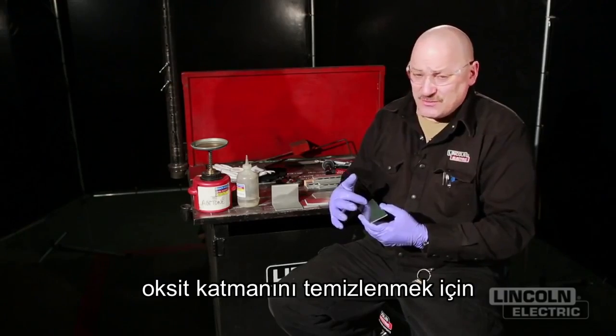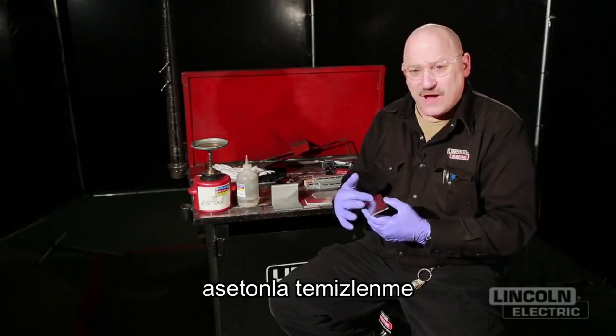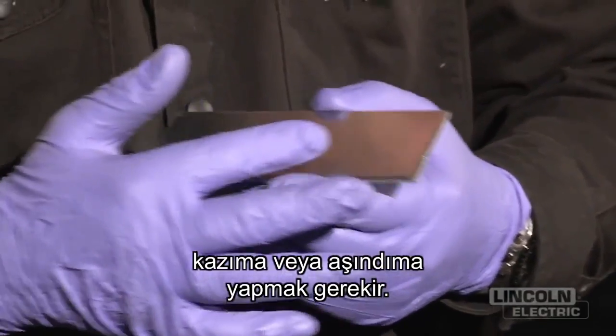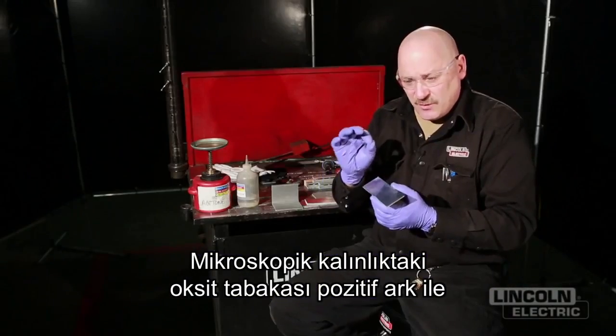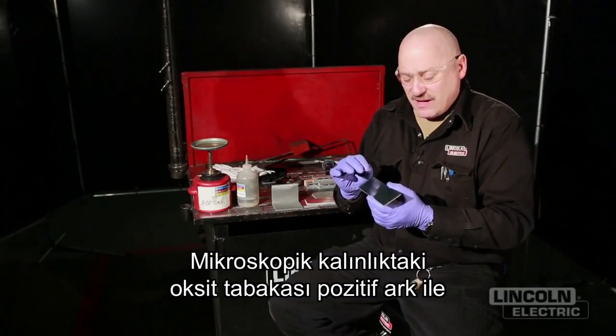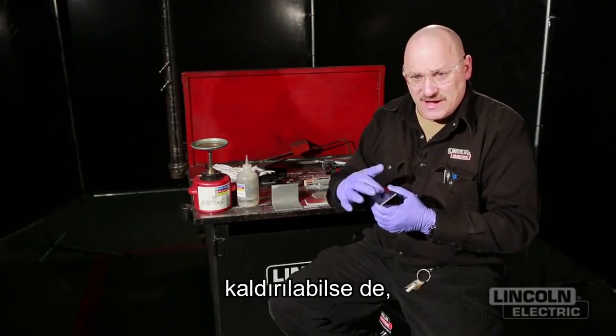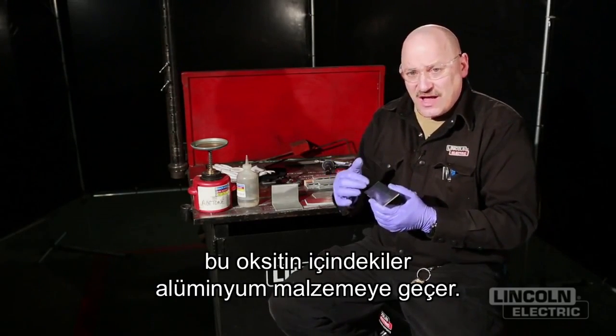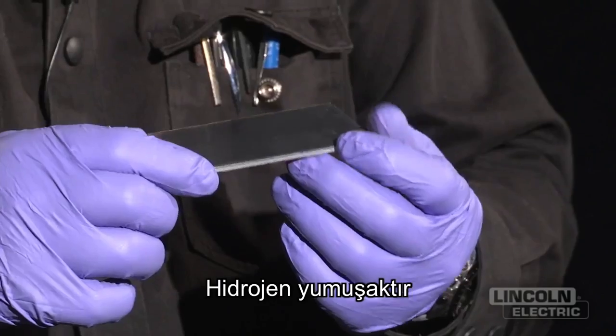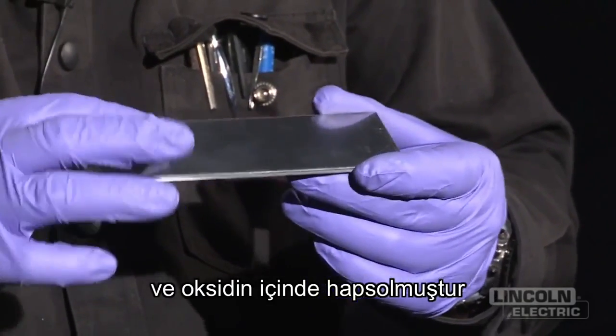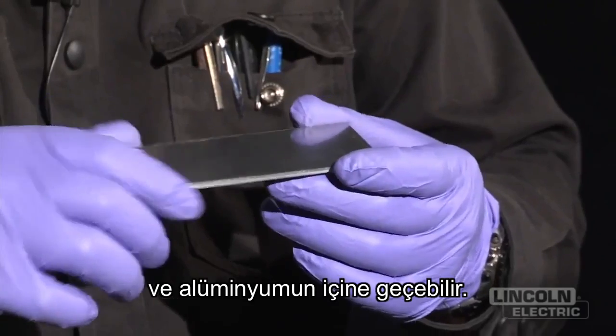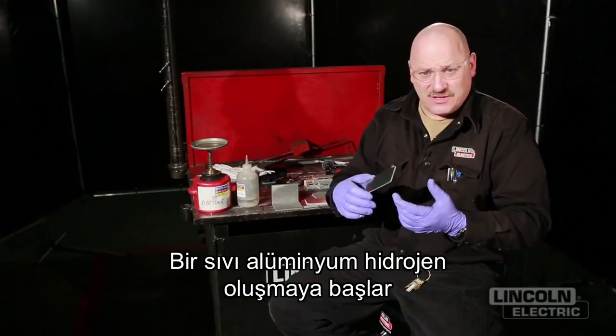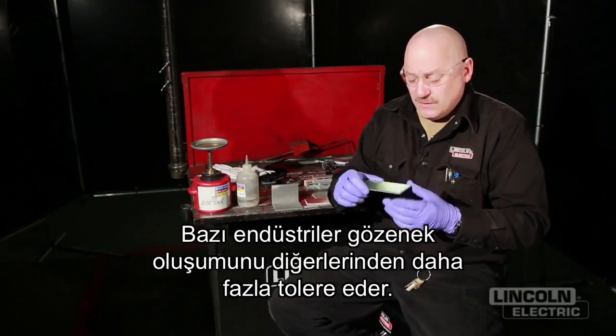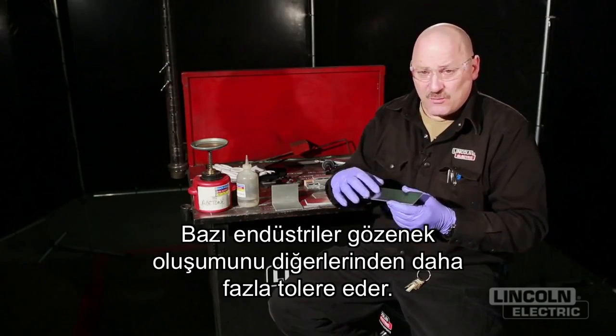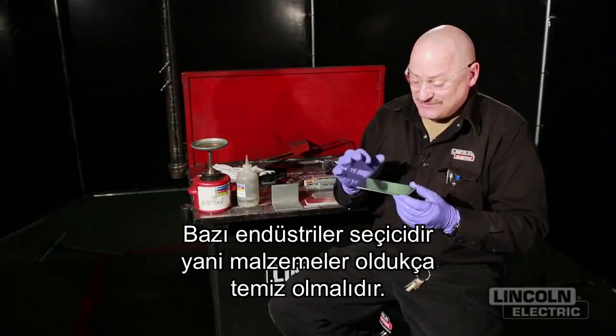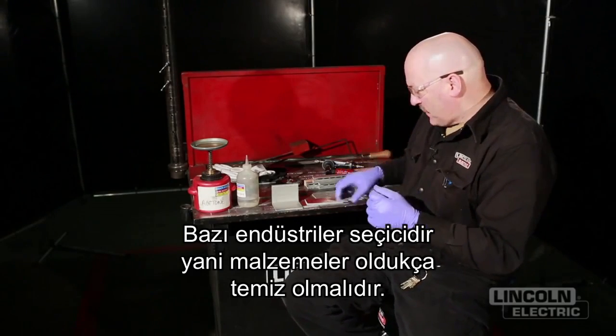Aerospace components and things, it would be acetone clean and also probably scraped down or abraded to remove the oxide layer, because even though that real thin microscopic layer of oxide can be removed with the positive polarity of the arc, what's inside that oxide actually goes into the aluminum. Hydrogen is one of the things that's often trapped in the oxide, so that can go into the aluminum, and in the liquid aluminum hydrogen takes up space, and that leads to holes or porosity in the weld. Some industries tolerate a little bit more porosity than others. Some are more picky, so things are going to have to be really clean in some industries.